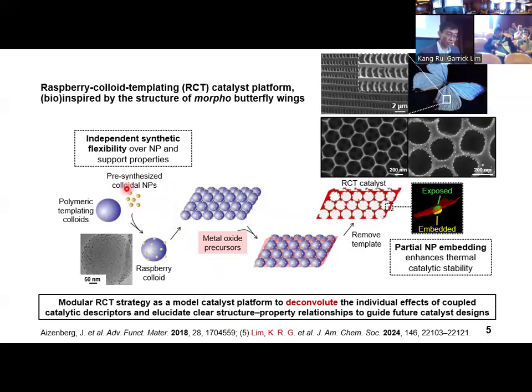You probably would, because the choice of the nanoparticles and the way you synthesize them is pre-synthesized. So all we need to care about is the nanocrystal synthesis phase, and the broad field where they study how thermodynamics and kinetics, for example, the choice of precursors, temperature, and nucleation characteristics, will be able to tune these spherical particles to something more to your liking, where you can choose to study shape or facet-dependent effects, and you will be able to load them. I think another comment I'd like to make is that the nanoparticles or nanocrystals, in your question, will be partially embedded, and that stabilizes the nanoparticles even more, although one has to be very cognizant of the effect that the support, because it has so much interface and contact with the nanocrystals, might change what will be the thermodynamic phase of these nanocrystals. Thank you.